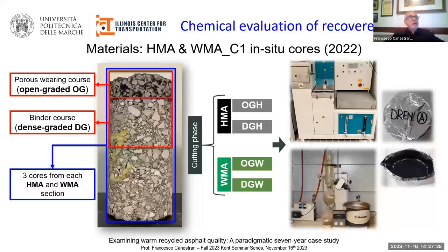Specifically, the binder was recovered from hot and warm mixtures prepared with the chemical additive C1, taken from in situ cores in 2022. After the binder extraction, the solvent was removed with the rotavapor equipment, as shown in the figure.